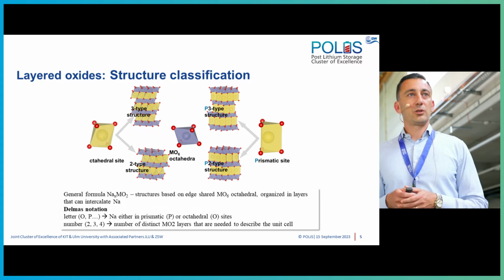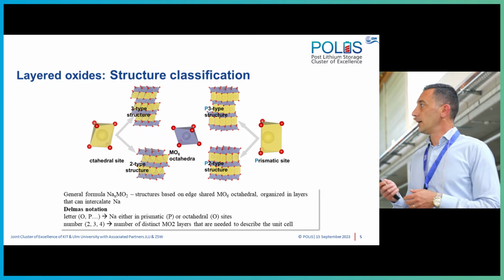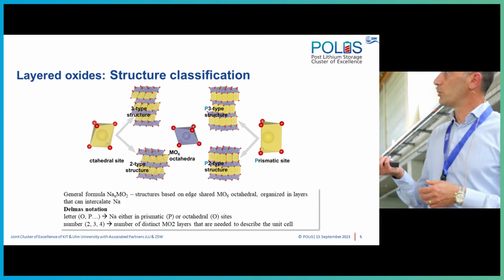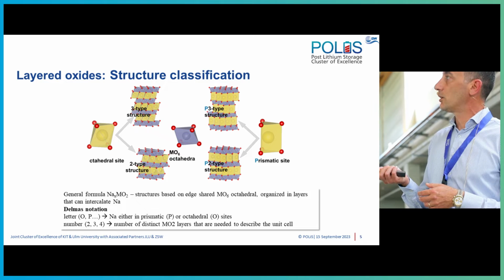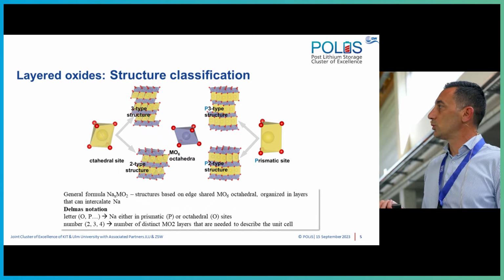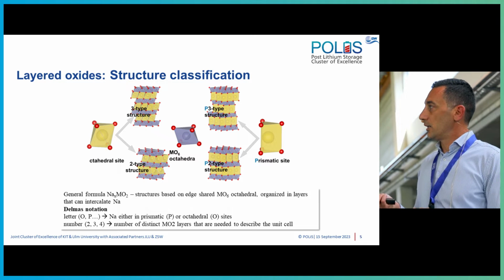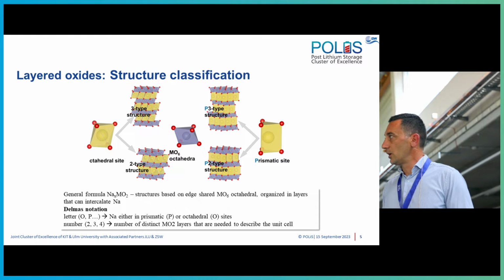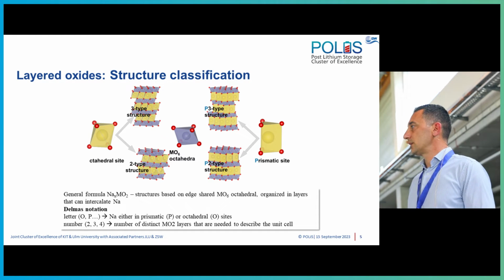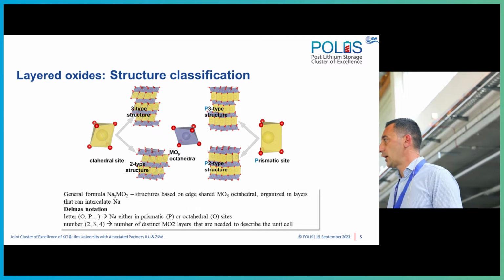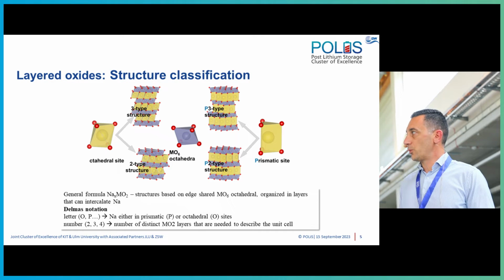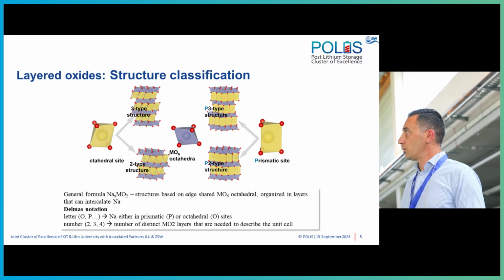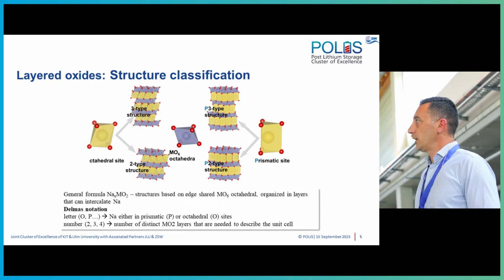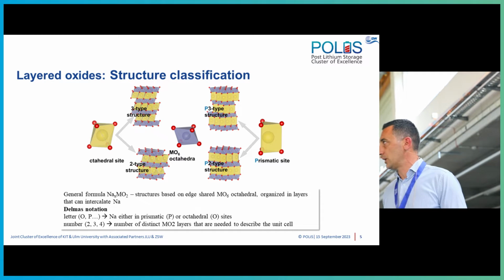I think most of you are actually familiar with the Delmas notation. Sorry, I realized that my PowerPoint didn't like to have the O at the beginning. So this would be an O3 type structure, and this would be an O2 type structure. In both cases, we have the sodium sitting on the octahedral sites. The difference is that in the O3, we have 3 MO2 layers needed to describe the unit cell, and in the O2 we need only 2 of them. Same thing for the P3 type structure and the P2 type structure. What is different is that in this case, the sodium will be sitting at the prismatic site.